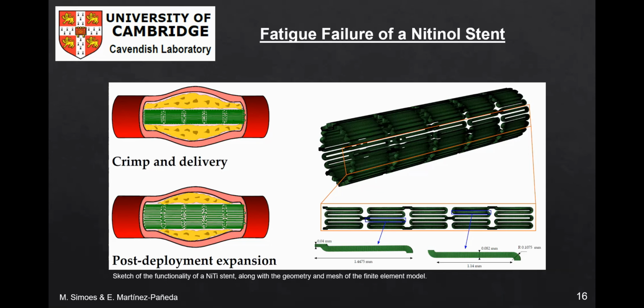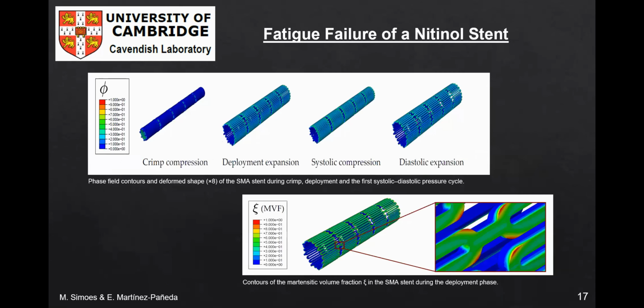However, fatigue resistance is often the limiting design criterion, since the stent is subjected to repeated contraction and expansion during the systolic and diastolic cycles. Current fatigue design models for stents commonly use Goodman's and other empirical methods to estimate the number of cycles to failure by extrapolating from the stress-strain state of the first cycle. We aim here at providing a more mechanistic approach using a phase field fatigue framework that can predict features such as SN curves or the Paris law as a natural outcome of the model. The finite element results obtained are shown here.